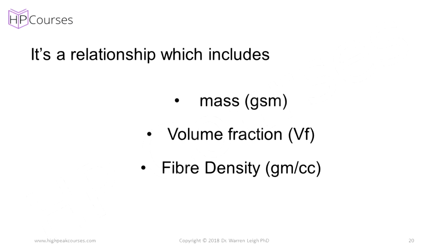For a composite containing 60% fibre and 40% resin, the volume fraction is 60%, or can be expressed as 0.6. The volume fraction is calculated from the weight of the fibre and the resin. It is a theoretical value and should always be checked by making a composite sample using the manufacturing process intended. The volume fraction value is based on a theoretical fibre packing model and is component geometry, process and fibre type dependent.